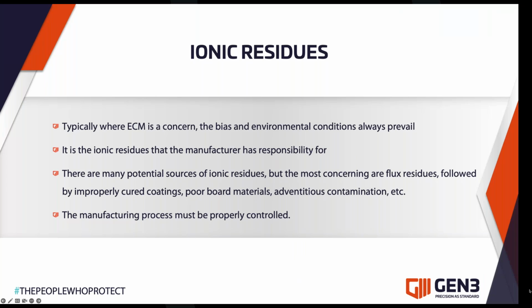So there are many possible sources of these ionic residues. Typically, most concerning, or the one we must pay most attention to, is the flux residues, because there are deliberately acids inside the fluxes which need to be controlled or removed or neutralized during manufacturing. Then there are other issues such as improperly cured coatings or poor board materials or just generally contamination. So there's a number of issues that must be controlled under a good manufacturing process to avoid this release of ionic ions.